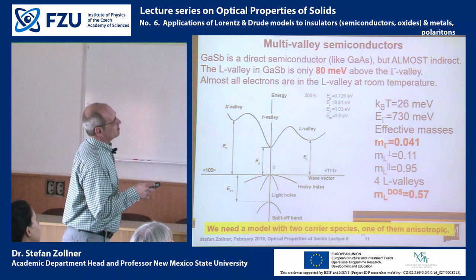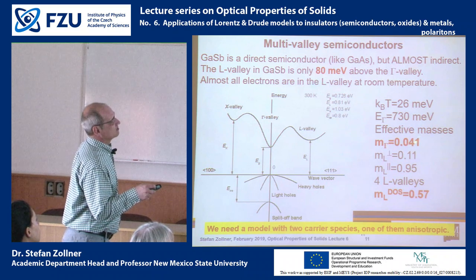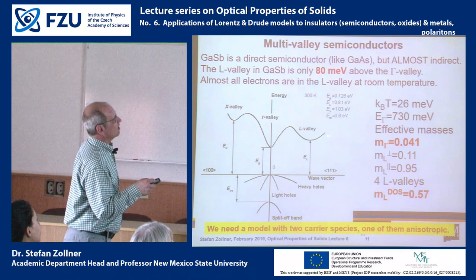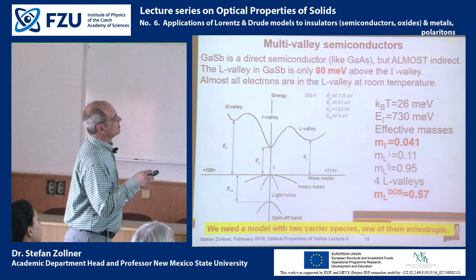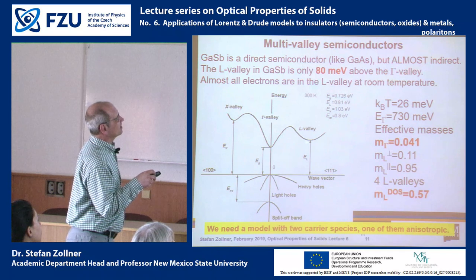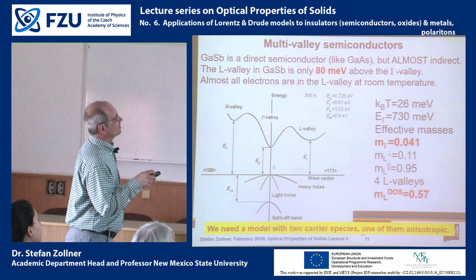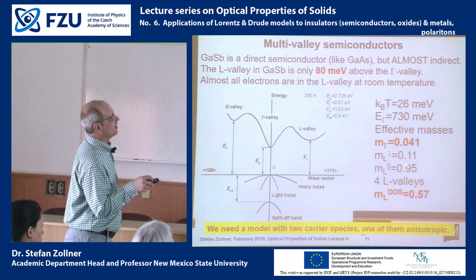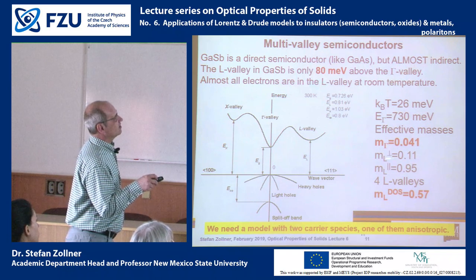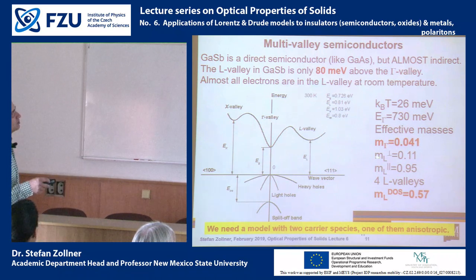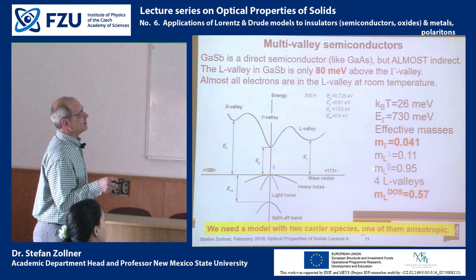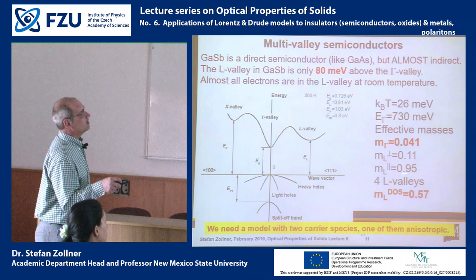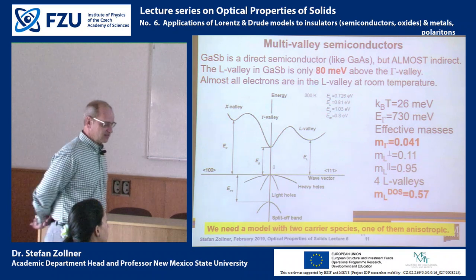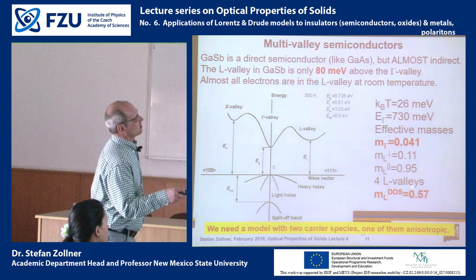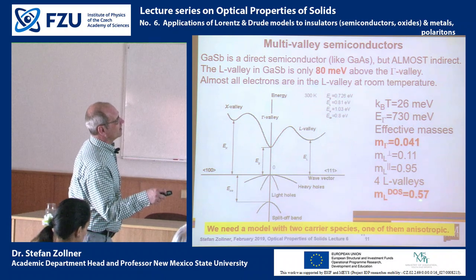The effective mass in the gamma valley is 0.041, and this L valley is anisotropic. There is a perpendicular mass going in and out of the plane of that slide, which is 0.11. And then there is a longitudinal mass, which is in the plane of that slide, which is 0.95. So what we do is we take this mass in two directions and this mass. And of these three masses, we take the geometric mean. That's the cube root of the longitudinal mass times the transverse mass squared. Then we have to consider that this L valley is at the boundary of the Brillouin zone, so we have four of these valleys, and then we're getting a density of states mass at the L valley, which is 0.57.